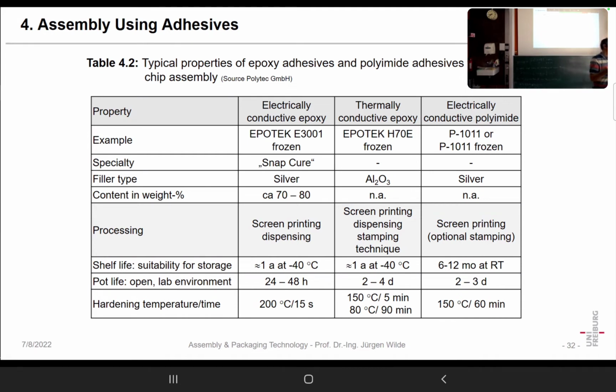Yeah, so you can say in polymers, the speed of a reaction is always when you increase temperature by 10 degrees centigrade, you double the rate, or you lower the temperature by 10 degrees, you halve the rate. And that's going to low temperature, for instance, having a material that is hardened, let's say at 200 degrees centigrade, you go down to minus 40, and then the material is just not reacting. The reaction is frozen, you say. That is just a question of kinetics.